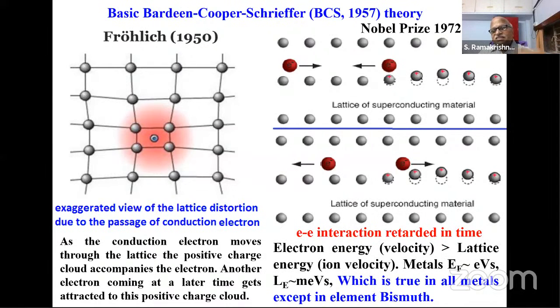Why? The Fermi energy of most metals is in electron volts, whereas the thermal energy, which is the Debye energy of the atoms, is of the order of milli electron volts. So the condition of BCS theory is well met. It's a theory of adiabaticity. The electrons move faster, the ions move so slowly that there can be an electron-electron interaction.